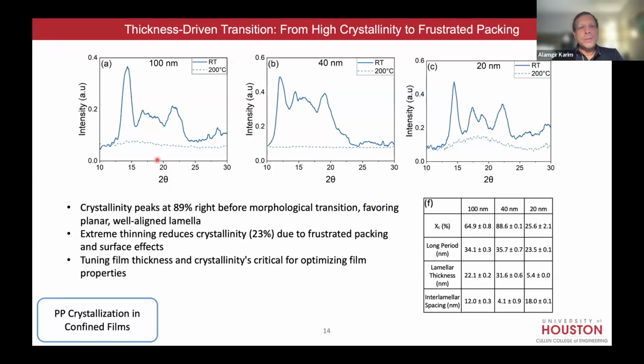Yes. All right. Okay, so GIWAXS, we go to Advanced Photon Source, which is a synchrotron at Argonne National Lab near Chicago. And at the grazing angle of incidence, you can determine the diffraction peaks in GIWAXS. So you get all these peaks that correspond to the crystal orientation and structure and so on. And we can calculate the degree of crystallinity. If you look in this box, 60-ish is kind of polypropylene, even though the bulk degree of crystallinity. What we find is that when you get below 100, you can get a significant enhancement. And we think that has to do with the confinement-induced alignment of the spherulite in the plane of the film. But if you go too low, it suppresses the crystallinity itself.